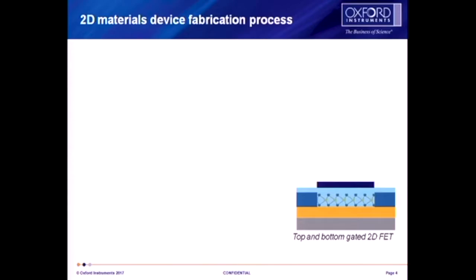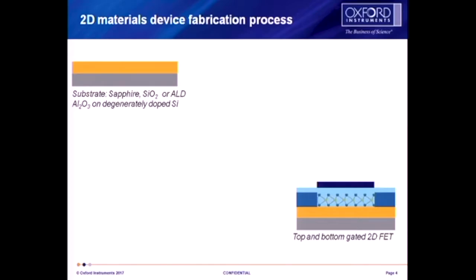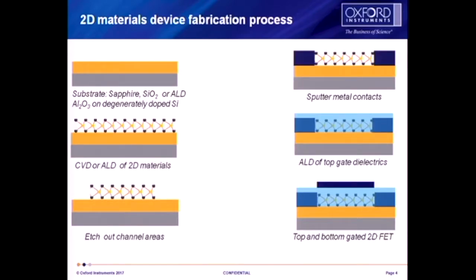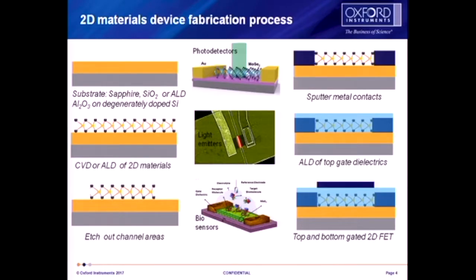If you look at how we make one of these devices, most people are just looking at a 2D FET type structure. And if I put this up, I can go through them quickly. You have a substrate, which can be sapphire or silicon dioxide, and we've used aluminium oxide. Sometimes it's doped. Then you grow your CVD or ALD of 2D materials, etch out your channels potentially using ALE, then deposit your metal contacts, then you do an ALD of top dielectrics, and you end up with your device at the end. Some examples of devices there are photodetectors, light emitters, and potentially biosensors.